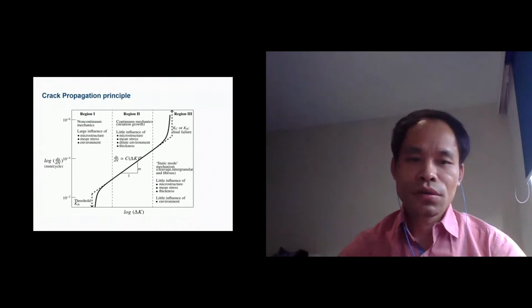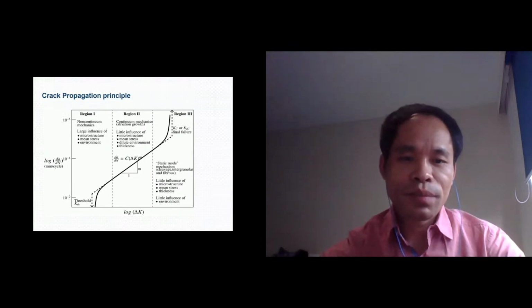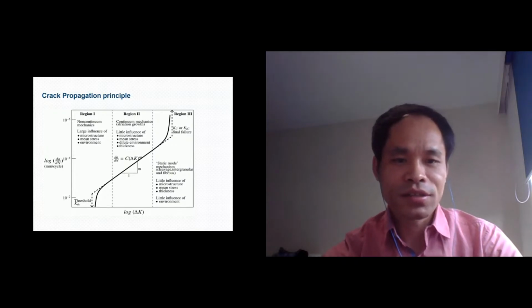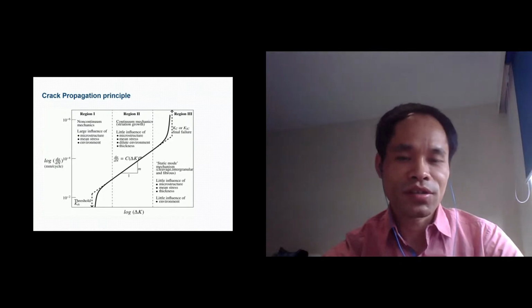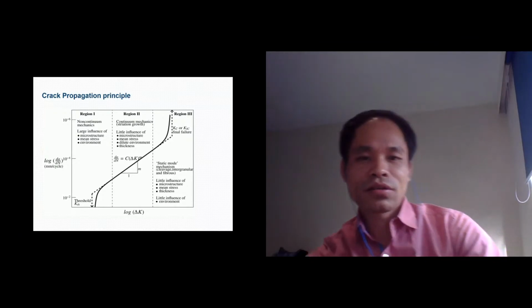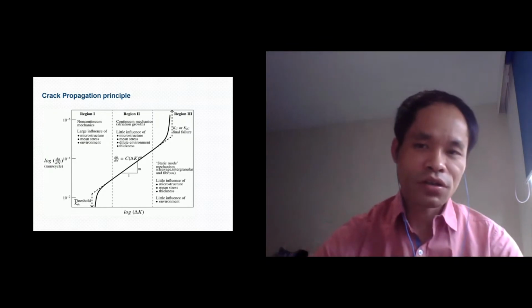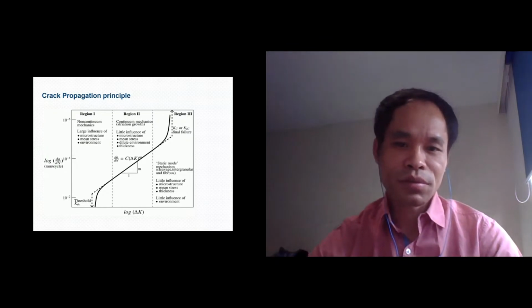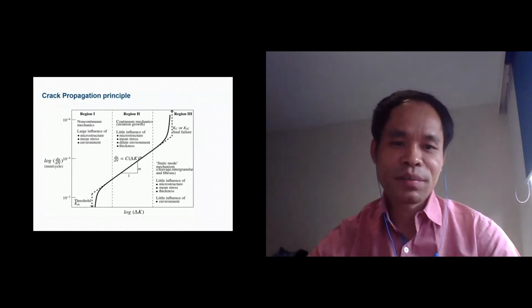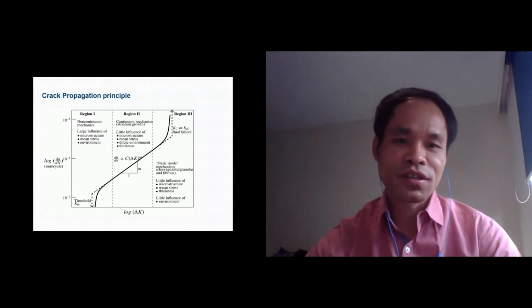According to what I have read from the papers, there is no proper way to evaluate this region as crack region 1, this region as crack region 2 and this as crack region 3. We cannot differentiate them, but according to the research with scanning electron microscope observations, it showed that there is a pattern of region 1, region 2, region 3. Okay.